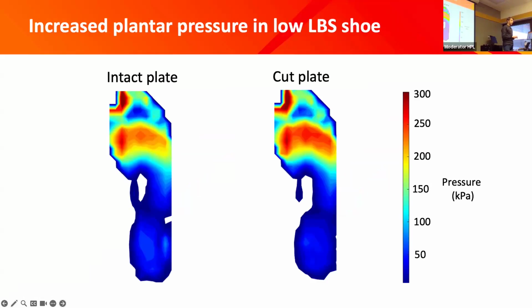This is also reflected in the plantar pressure. So if we look at a representative subject here, this is the plantar pressure at the time point of peak strain. So this is just a heat map of the pressure under their foot. Red is high, blue is low. You can see that the intact plate condition here is slightly less red compared to the cut plate condition, where the area grows and the magnitude also gets a little bit higher too. So that's probably what's driving those increased forces.